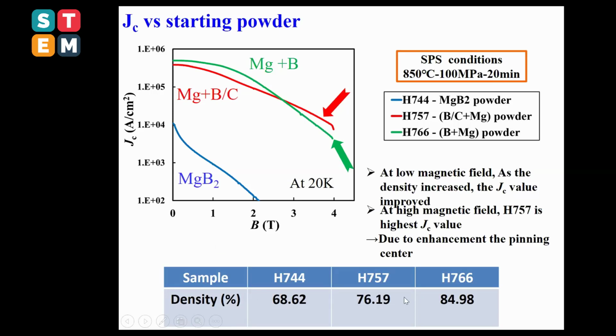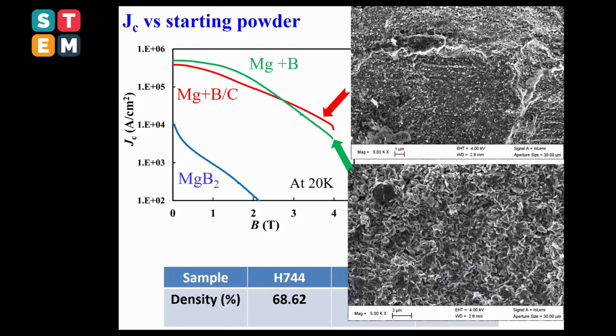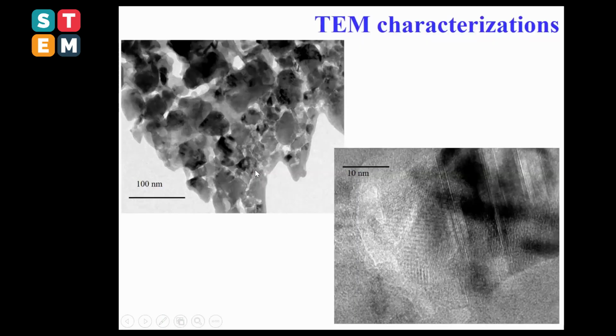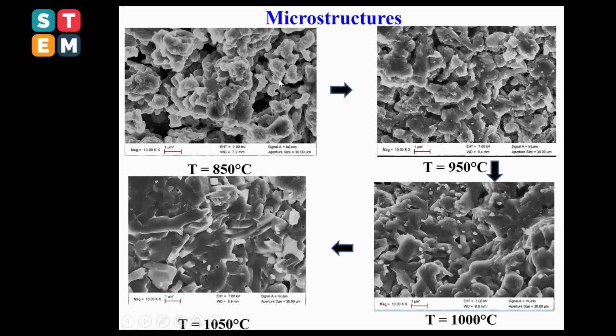But in that case, you can clearly observe again the JC increase here because we improve the density of our material. But the answer from this is here. When you look at the microstructure on the board curve, you have some small grain size in that case compared to that one. That means we improve the pinning in this case compared to that one. This is one of the reasons where the JC really increased. Or if you compare with the magnesium diboride prepared in the same condition, the microstructure was here. You can see the grain size is quite high. You have a very big grain size and also quite porous materials.